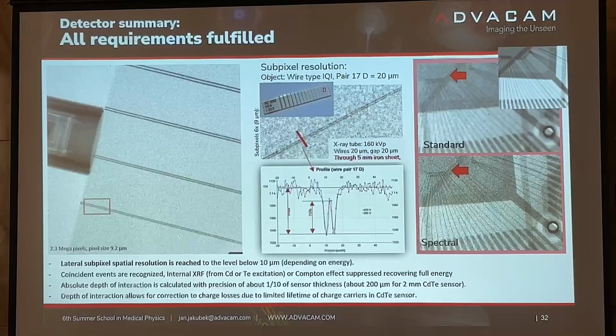And just to show you the result, this is the result. This is this IQI measure or standard, which was described by Uwe here. This is the first generation of that standard, which went down to 50 microns, and we distinguished those wires perfectly. And the second generation goes down to 20 microns. This is this pair of fibers, 17D17, and even those are recognized well. So we still distinguish it. That means that we cannot measure the resolution of our detector with this standard. So the standard should be updated.